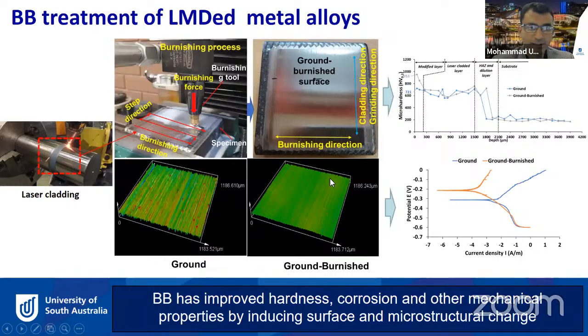And these are some of the results we have. You can see here that after the ball burnishing, surface roughness has improved a lot, significantly, I would say. And similarly, we also looked into the hardness improvement. We can see that at the top surface, the surface hardness has improved significantly, and we looked into the corrosion resistance of the material as well. And we can see here the corrosion resistance, which is basically a higher potential or less current density, means that the material has a higher corrosion resistance. So this is another nice outcome of this treatment as well.